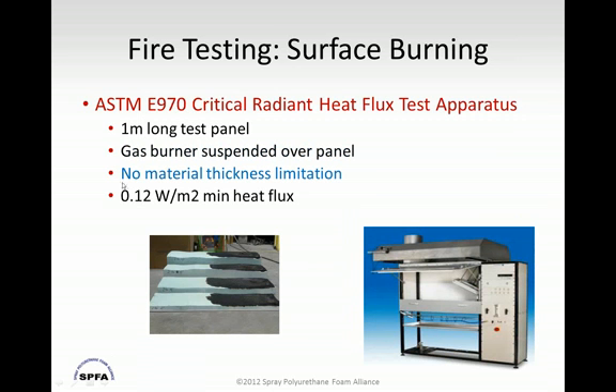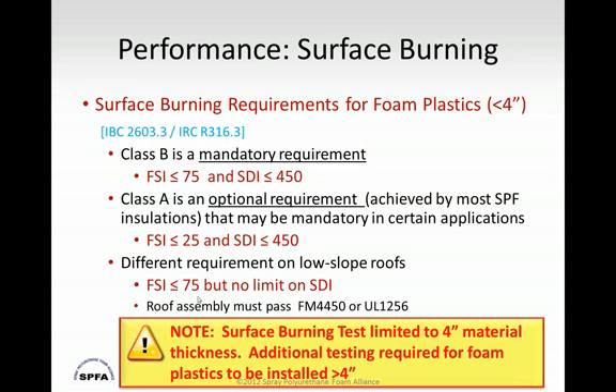In this chamber, there is really no practical material thickness limitation. This bed here can be raised and lowered so that it's the standard distance above that burner to give you the amount of heat flux applied to the surface of the material. And here, actually, we've shown this with foam plastics. Here's a closed-cell foam of different thicknesses, and we can see that we get some pretty consistent results from this test regardless of the thickness of the foam.